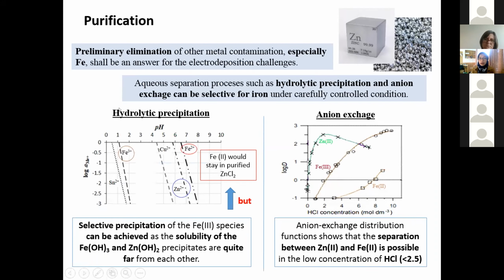Here we can use hydrolytic precipitation and anion exchange, because theoretically, we can see the hydrolytic precipitation in this range of pH. We can separate the zinc here and the iron here. So we can put maybe sodium hydroxide in the solution to precipitate the trivalent iron here. But then let's see the challenge with the anion exchange. What is the drawback of this process? The trivalent iron will be lost because of the precipitation. We will have it as a precipitate.